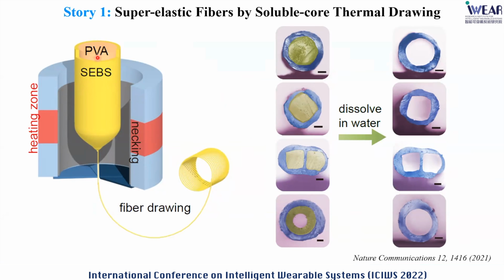And we use a PVA as the part that can be used to hold the stress during the thermal drawing. So we use the PVA to design the structure, and on the outer surface of the PVA, we use the SEBS to cover it. So during the drawing process, the stress is mainly applied to the PVA. And for the SEBS, it just naturally flows along the surface of the fiber.